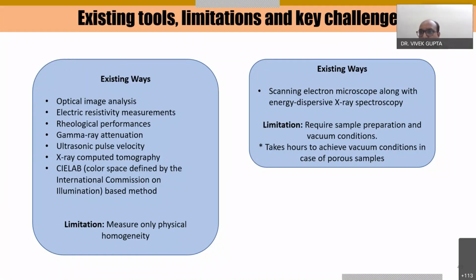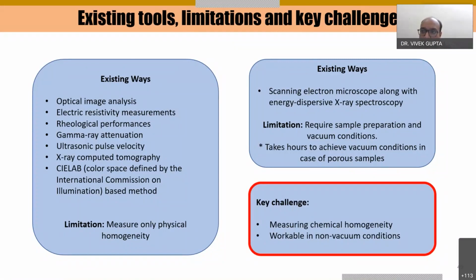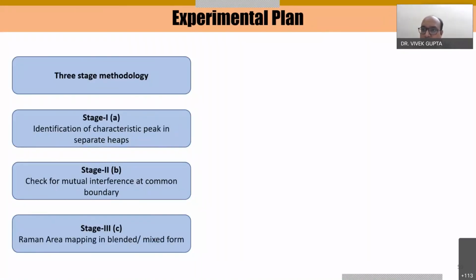And specifically, when we are going for unfired bricks, it takes hours to achieve the vacuum condition in the case of porous material. I have used the SEM, and it takes hours to get the vacuum conditions and is difficult to take the SEM images. So the challenge was we want to measure the chemical homogeneity and develop a tool which should be workable in non-vacuum conditions, because in the vacuum condition it is taking so much time. So what we have done, we have used Raman spectroscopy.